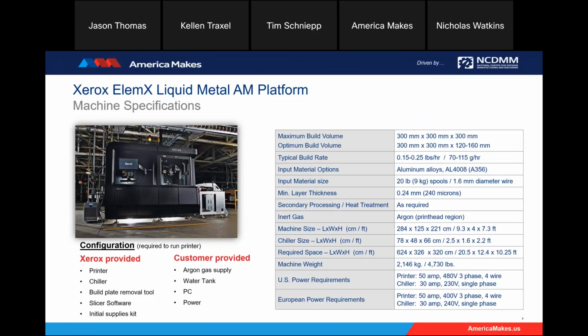And then on the right-hand side of the slide are the specifications. So the build chamber itself is 300 by 300 by 300 millimeters, about 12 by 12 by 12 inches. Though we do at this stage recommend a slightly lower Z height. The reason for that is it does depend a little bit on part geometry, but we rely on heat transfer from that hot build plate into the part to keep the part surface, the build surface, at the optimum temperature. And we found after that 4 to 6 inch range that because aluminum transfers heat so well, it cools down relatively quickly and we don't get as good droplet adhesion, and we start to see some variability in mechanical performance at that point.